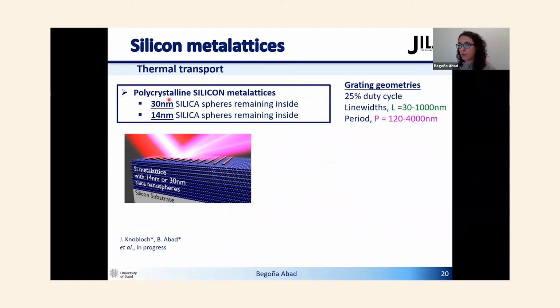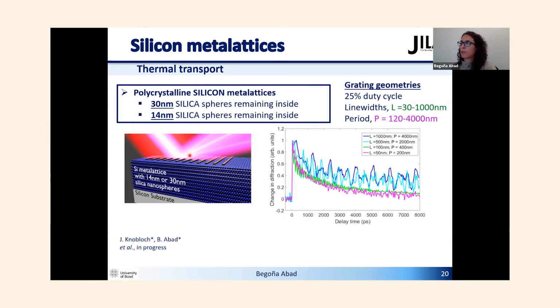As I said, we measured two samples. One is made of 30 nanometers diameter spheres, and the other one is 14 nanometers in diameter. So we have different gratings with different periods and line widths, and we do our pump-probe spectroscopy. When we do that, we get this type of signal, which is really good in terms of signal-to-noise ratio. We can clearly see the acoustic waves and the thermal transport.